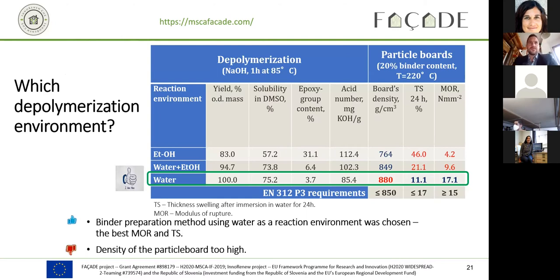And to start to produce the binder, at first we selected the depolymerization environment, which environment we should use: ethanol, water-ethanol mixture, or pure water with potassium or sodium hydroxide. And we concluded that the binder preparation method using water as a reaction environment showed the best properties for mechanical and moisture resistance. Still, there was a problem about the density of the particle board. It was too high because we set our target to 850 kilograms per cubic meter.